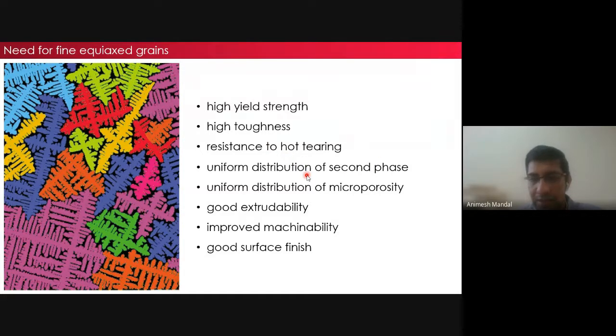If you have fine grains, you also have a uniform distribution of the other phases and a uniform distribution of the microporosity. Then you can improve the extrudability of that particular alloy, machinability increases many fold, and as a result you get a good surface finish. So generating a very fine grain material is crucial to achieving a good casting. The very objective of all foundries should be to refine the grains as much as possible.